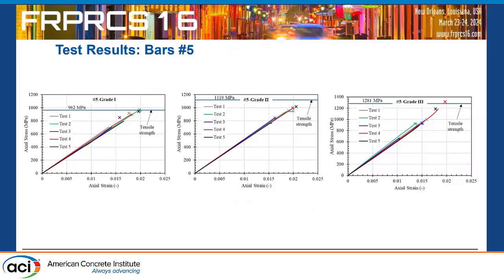So here are the results for each group. Number 5 bars, grade 1, grade 2, grade 3. The horizontal line shows the tensile strength reported by the manufacturer, and these are the compression results. So you see that the compressive strength is very close to the tension. We are in the range of 90% to 100%. Sometimes you could even go a little bit higher than tensile strength. So that's the reality that we are getting now.